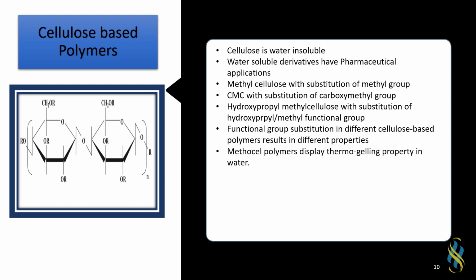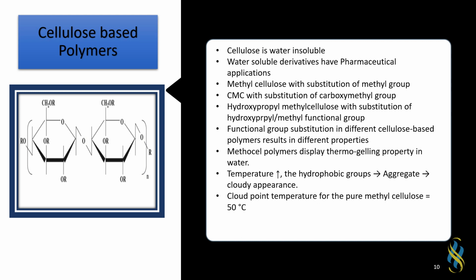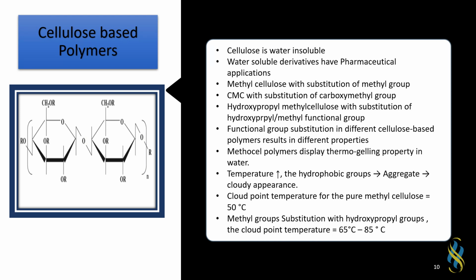Methocel polymers, including pure methyl cellulose and hydroxypropyl substituted methyl cellulose, display thermogelling property in water. As the temperature of the solution increases, the hydrophobic groups of these polymers start to aggregate. As a result, the polymer solution will assume a cloudy appearance. The cloud point temperature for pure methyl cellulose with no hydroxypropyl substitution is about 50 degrees Celsius. As the pure methyl groups are substituted with hydroxypropyl groups, which have better solubility in water, the cloud point temperature shifts to higher temperatures and ranges from 65 degrees Celsius to 85 degrees Celsius, and it forms different forms of Methocel, which are commonly known as Methocel E, F and K.